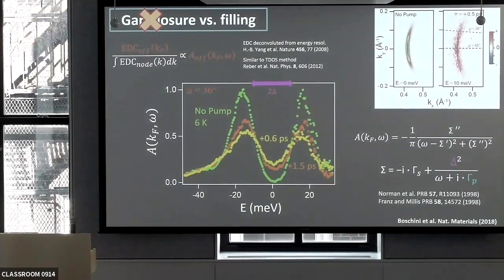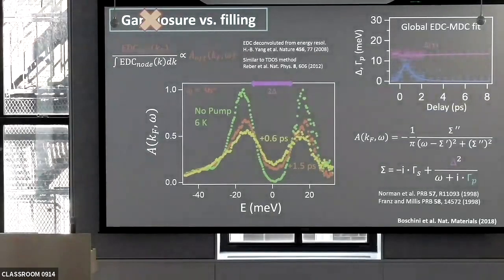Going forward with this, you can do a more detailed analysis in terms of this spectral function, in particular follow the delay evolution. You see that the gap is changing about 10%. That change of 10% is consistent with the electronic temperature that Fabio estimates by looking right at the node. The biggest change is in the gamma, and interestingly, this is what defines basically the quenching, if you like, and the recovery as well. It's really that time dependence.